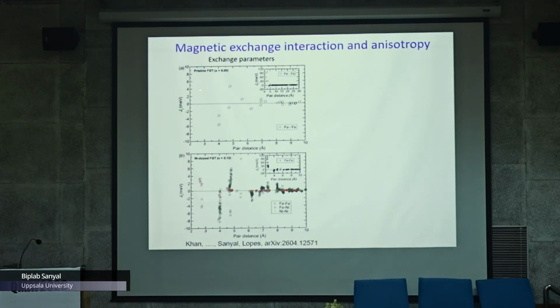So what I am showing here is the pristine FGT where there is no nickel atom. This is the isotropic exchange parameter as a function of distance between the pair of iron atoms. In the inset, you see that the first neighbor interaction is very strongly ferromagnetic. Plus means it's a ferromagnetic exchange, very strong here. And then the expanded part is shown in this plot. So you see that there is an oscillation between ferromagnetic and antiferromagnetic exchange here.